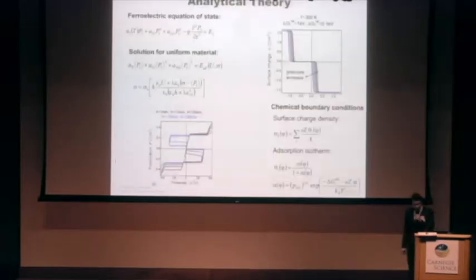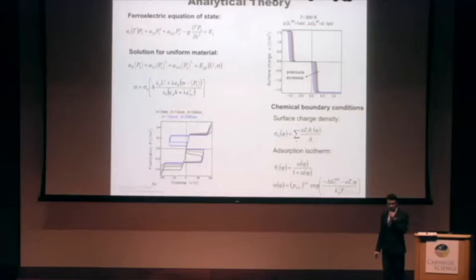So how do we actually try to model this? We take our standard ferroelectric equation of state, which is shown here, and we don't do anything to it. We don't add any terms to it. All we do is change the boundary condition. The boundary condition now is, instead of the electronic screening boundary condition, a chemical boundary condition, and that's given by this surface charge density here.